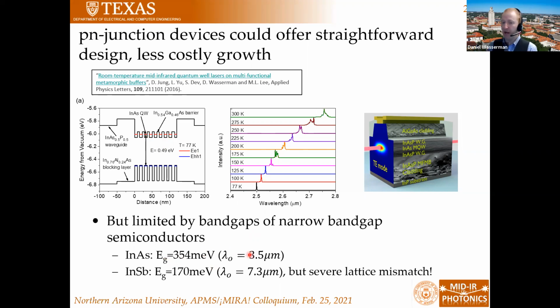So you could perhaps move to indium antimonide, or InSb, which has a band gap at 7.3. But InSb's lattice constant's way out there, so you can't grow it on any real substrate. So that becomes a real problem, and there's no good band offsets to use with it. So InSb is not a great material, and even if you could grow InSb structures, it still only gets you out to 7.3. So as much as we would like to be able to make a simple PN junction with a quantum well in it, we're not going to hit the long wavelength infrared, the 8 to 12 micron range, with these types of devices.